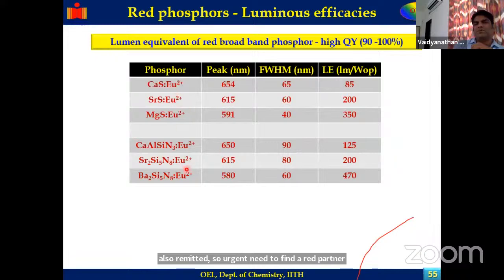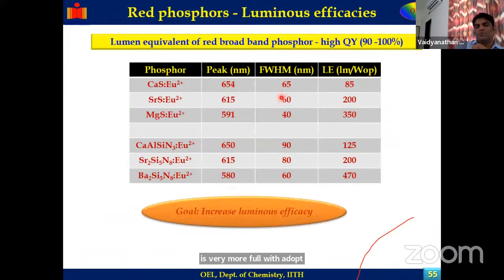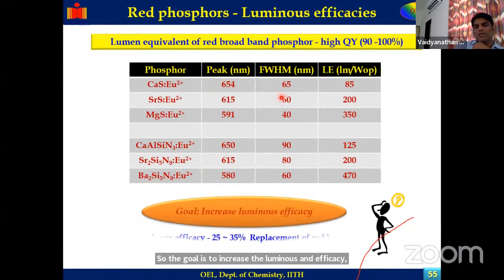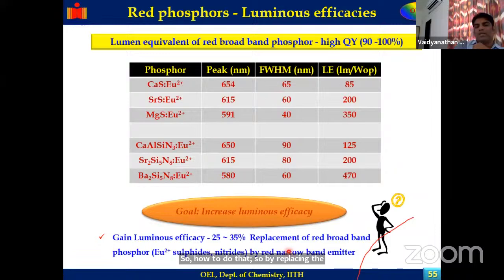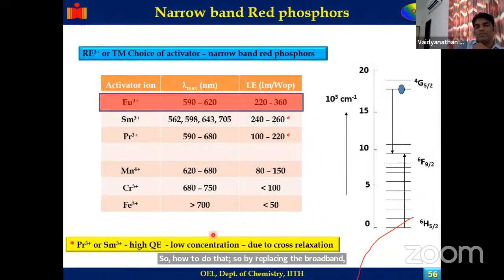There are some phosphors known to emit in the red region, whose lumens output is more. In the case of europium 2+, it is good. However, the width of the peak is very large; the full width at half maximum is large. So the goal is to increase the luminous efficacy. How to do that? By replacing the broadband emitters with narrow band emitters, one can gain 35% of luminous efficacy.